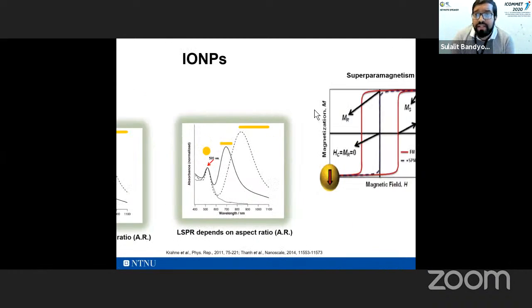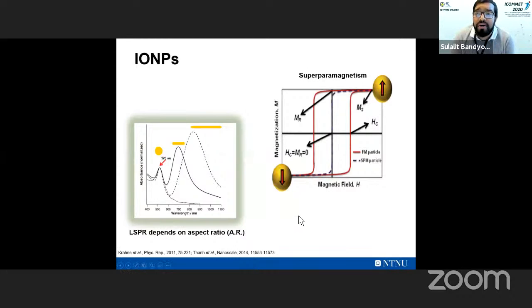And the other kind of nanoparticles which I'm going to talk to you about today are the iron oxide nanoparticles. The major reason why they have been of such interest is their superparamagnetic properties. What it means is, if you're familiar with this M-H curve, which is the hysteresis curve for magnetic materials, a superparamagnetic material is the dotted line shown here, meaning the hysteresis area is very low, almost negligible. It has high magnetic saturation. It behaves as a magnetic material only in the presence of a magnetic field. The moment you take it out, it loses its magnetic properties.